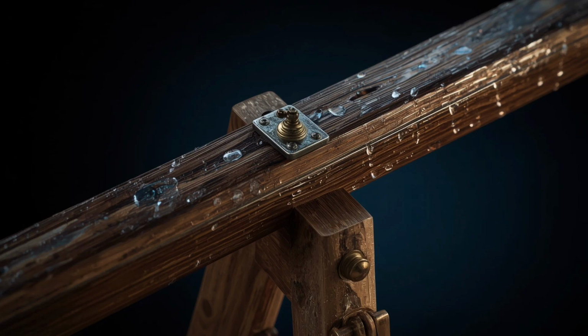They examined each component in detail. The wooden platform showed visible moisture accumulation on cold, humid mornings, a thin film of condensation that dried as the room warmed. They measured the platform's dimensions at different times of day using precision calipers. The thickness varied by nearly 1/8 of an inch between the driest afternoon conditions and the dampest pre-dawn conditions.